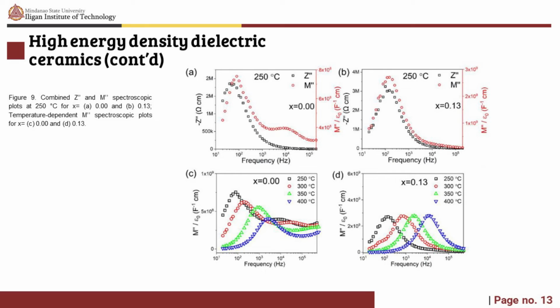It is noteworthy that the M peak height is largely invariant in the temperature range from 250 to 400 degrees Celsius, as can be seen in 9d, which is consistent with the flat epsilon-versus-T response observed from fixed frequency dielectric measurement. While in figure 9, the temperature-dependent spectroscopic plots of M for x equal to 0.0 and x equal to 0.13 are displayed in figure 9c and d.